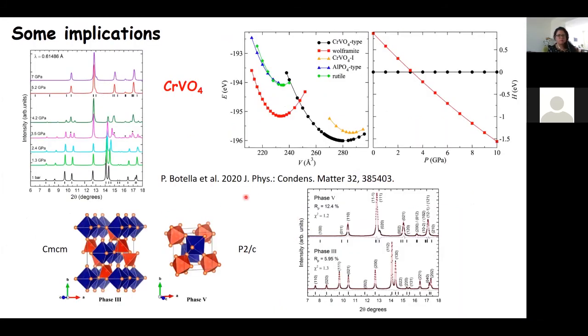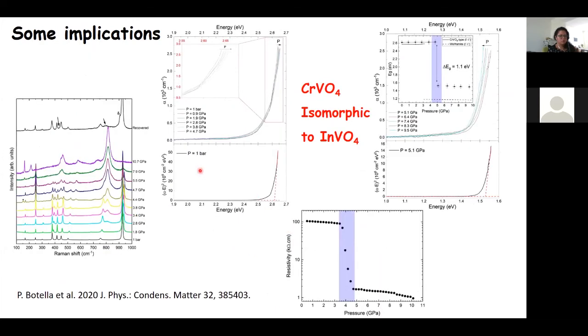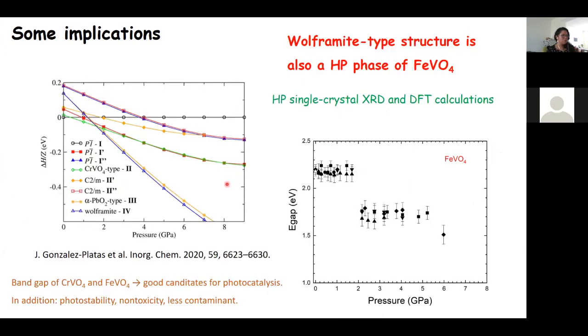But not only that, not only did we find this happened in chromium vanadate. More recently, this is ongoing research, we have studied iron vanadate, which at low pressure is similar to chromium vanadate and indium vanadate. And in this compound, we have seen that it undergoes two phase transitions, but the second high pressure phase is also the same wolframite phase that we had observed in chromium vanadate and indium vanadate.